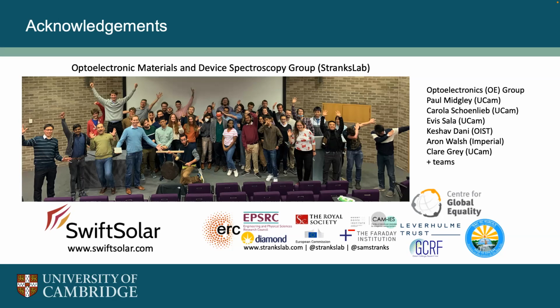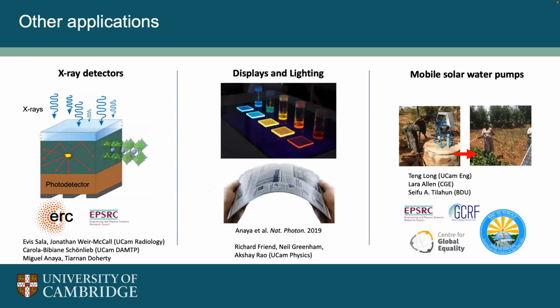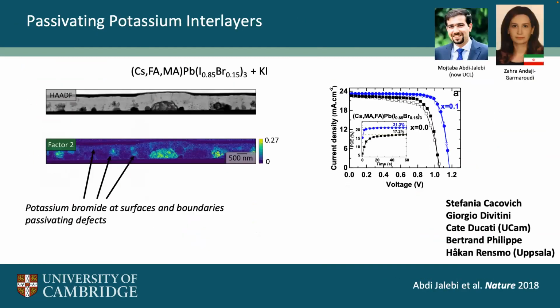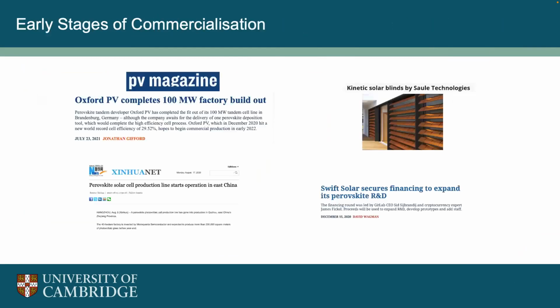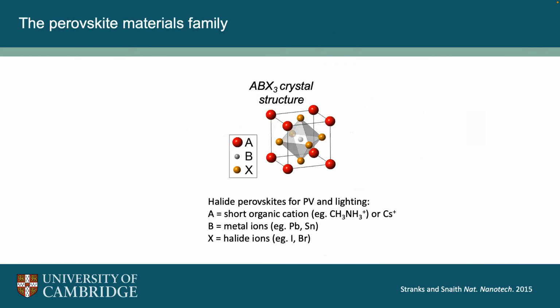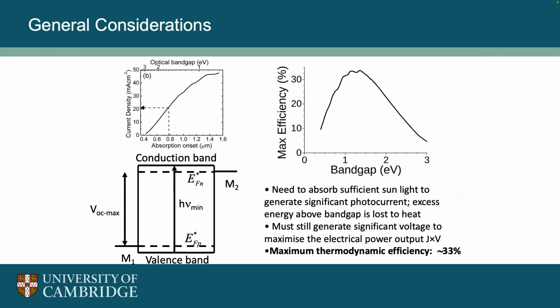Yep, so good question. The best perovskite cells I showed, or at least the records, are 26%. When you move to the yellow ones, they're more like 10 to 12%, something like that. So you are seeing quite a drop in efficiency. In fact, we can go back to that efficiency plot with band gap. Yeah, so you can actually see the drop-off as you move. 2 eV on the right there is somewhere in the yellow absorption region, so it's dropping off to 10 to 15% at its absolute best. So you do pay a penalty, but if you can have PV in more places, it might be a penalty worth paying.